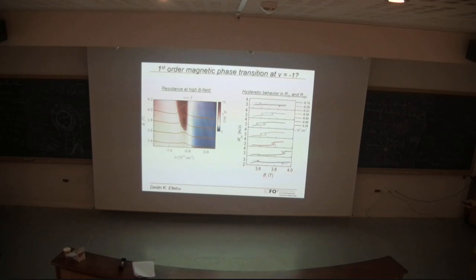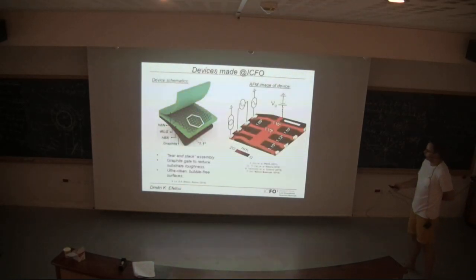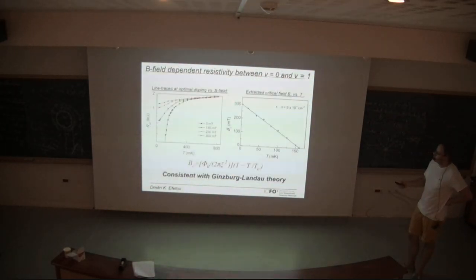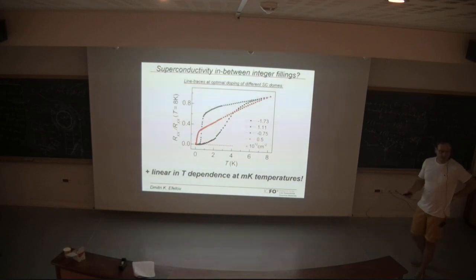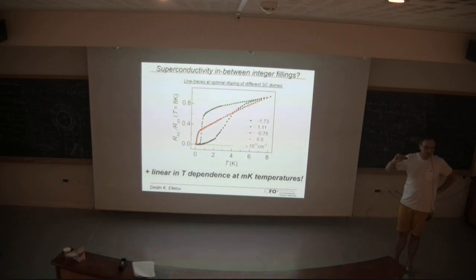So this is still a story in progress. First of all, that highest TC superconductor, this is the black line, and you see it's a very broad transition, very broad transition, and then you can see the superconductors close to filling 1, they're much sharper.